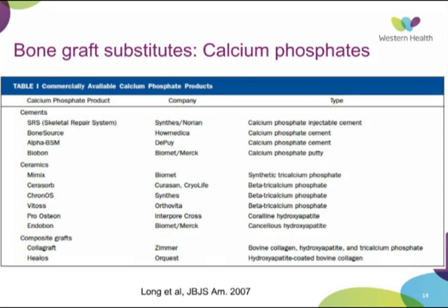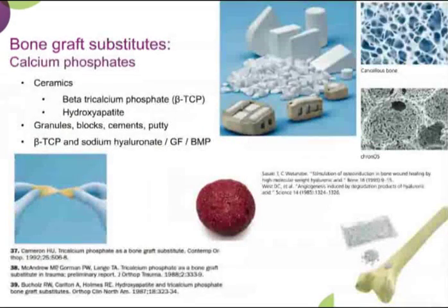also just over here, there's different forms. So calcium phosphate cements, the beta-tricalcium phosphate, as well as the coral derivative hydroxyapatites, and synthetically produced hydroxyapatite. So bone graft substitutes, they are also conductive, as in they provide a scaffold for the bone formation and a matrix for the cells. They only have osteoinductive properties if an extra factor is added, for example, some of these growth factors or bone morphogenic protein, and sodium